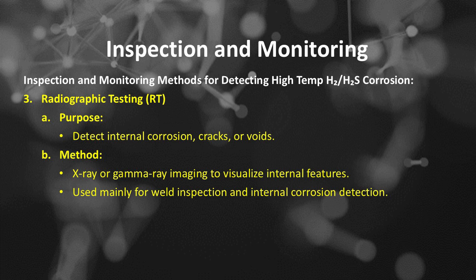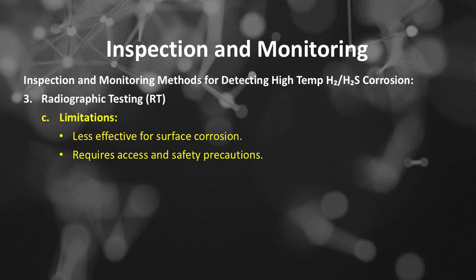Inspection and monitoring methods. Number 3 is radiographic testing, or RT. This is purposed to detect internal corrosion, cracks, or voids. The methods of radiographic testing include X-ray or gamma-ray imaging to visualize internal features, used mainly for weld inspection and internal corrosion detection. The limitations of radiographic testing include: less effective for surface corrosion, requires access and safety precautions.